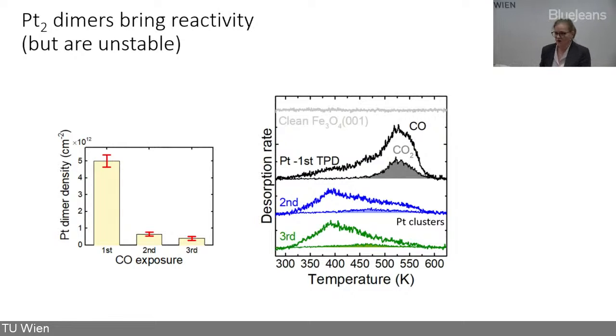First, they need to take the oxygen from the substrate, and if a cluster is less in contact with the oxide substrate, that's harder. But also, if you pay attention, these curves are shifted to a lower temperature. The CO2 desorption needs a certain activation energy, and when the CO desorbs from the platinum clusters at lower temperatures, there's no carbon monoxide left anymore for this reaction, so there's no CO2 anymore.